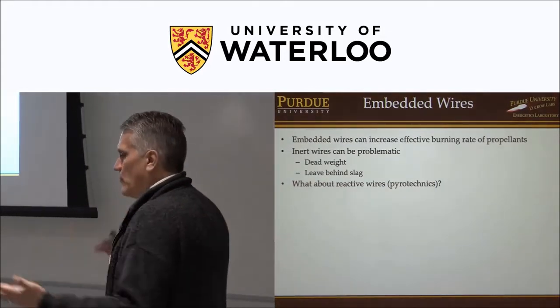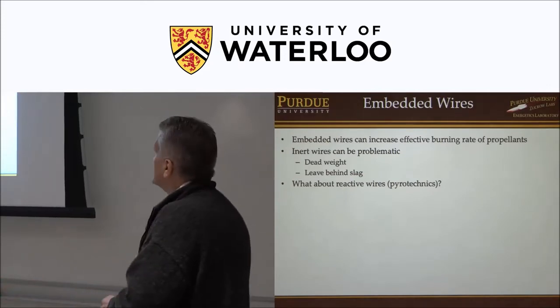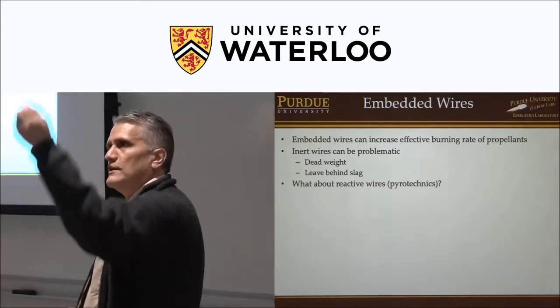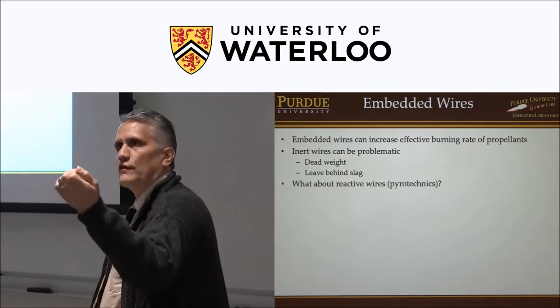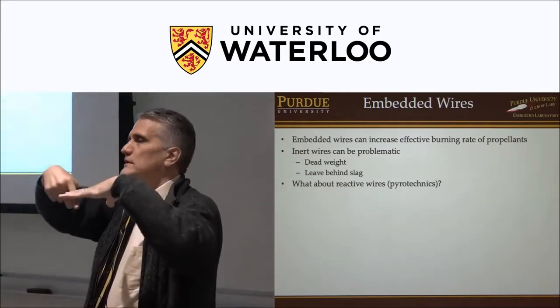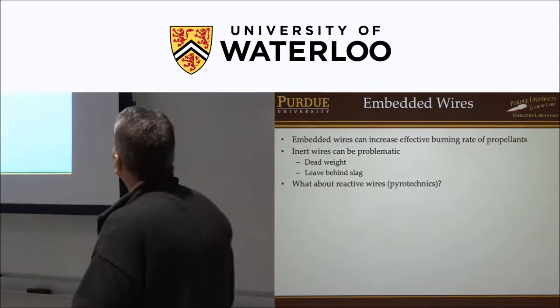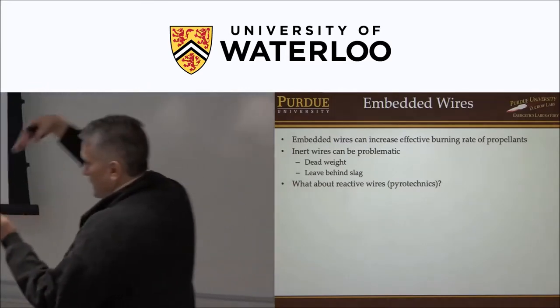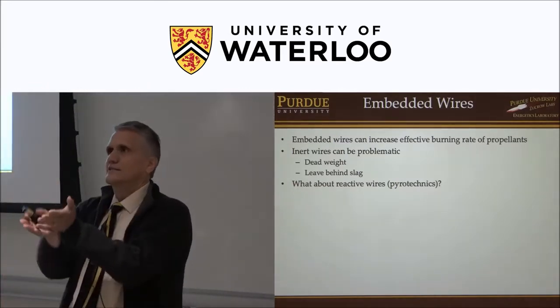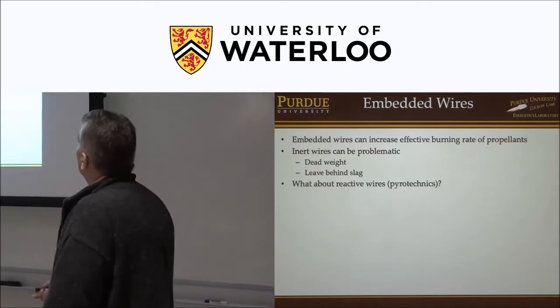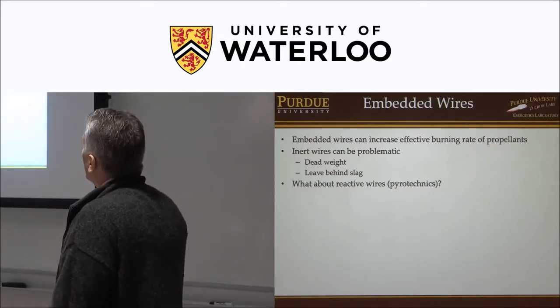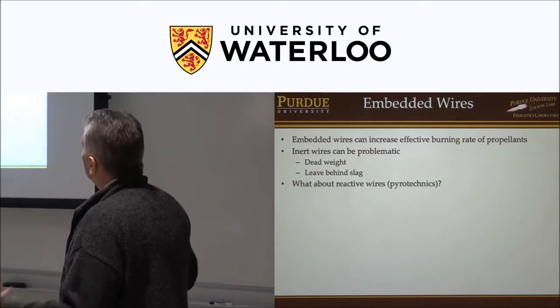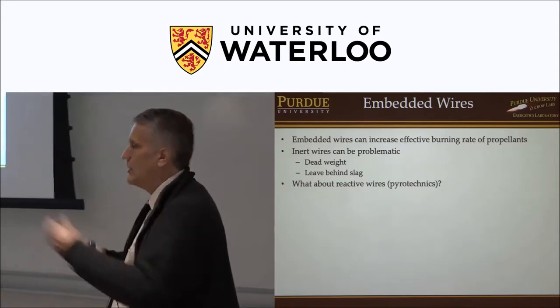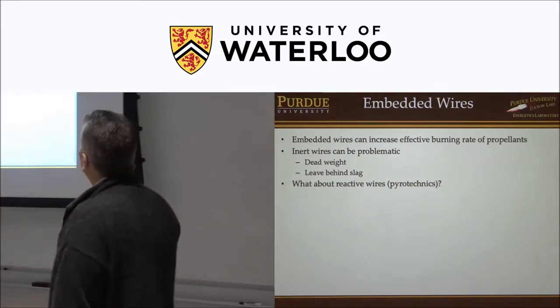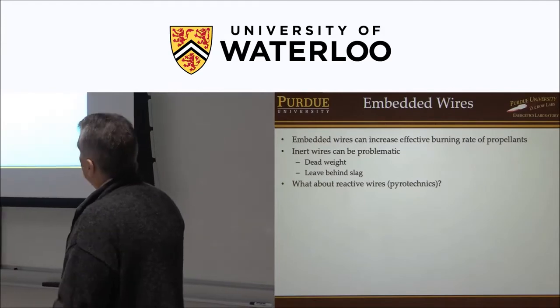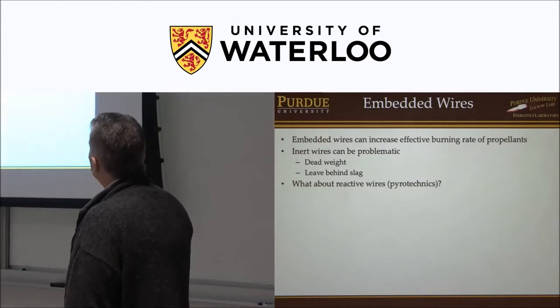So embedded wires are sometimes used in solid propellants to increase the effective burning. They increase the heat conduction along those wires. So think of a propellant with some, could be copper, aluminum wires, whatever. And as that heat conduction is improved, it creates these kind of cones, these divots. The inert wires can be problematic, though. There's dead weight. They leave slag behind. They have clunky products that go out through your nozzle. Could corrode your nozzle or erode your nozzle.